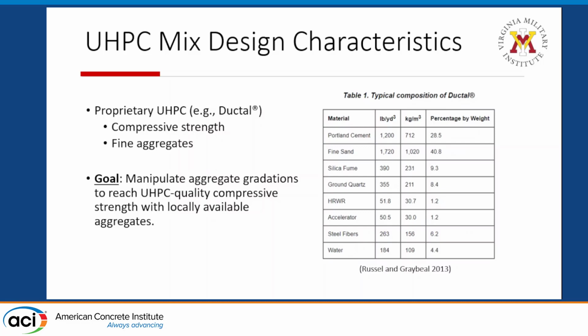The fine aggregates used in Lafarge's Ductal® UHPC range from about 600 micrometers to 0.1 micrometers, so incredibly small, and it creates a really dense packing mixture. So again, my portion of the research, the mix development, was focusing on these fine aggregates and figuring out a way to create a really strong concrete basically in my backyard.